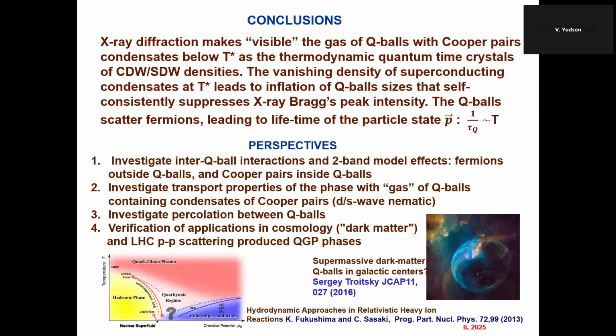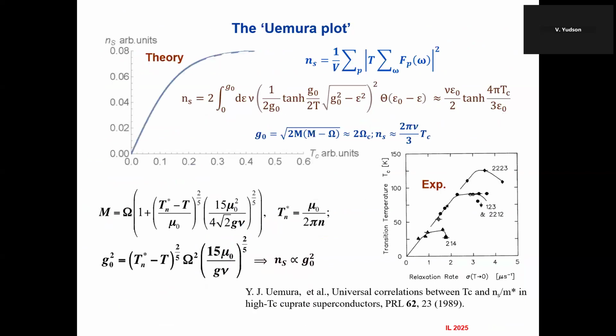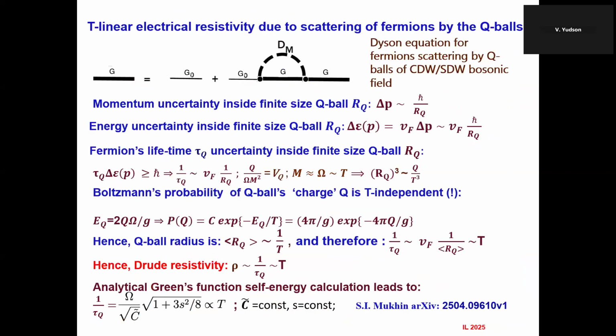Is it possible to understand on the fingers why the resistivity is linear in T? So you see, if I consider scattering of an electron by a Q-ball just perturbatively, like the Fermi golden rule, then I would expect that the scattering rate is proportional to the square of the amplitude of M. And the amplitude M is proportional to temperature. So I would expect, naively, that the scattering rate is proportional to temperature squared.